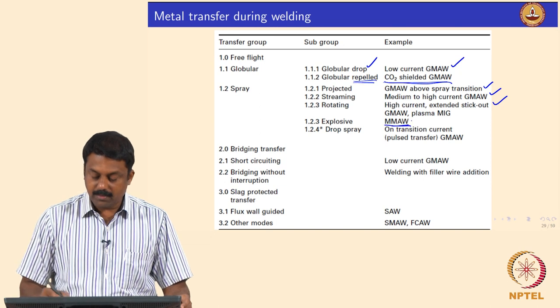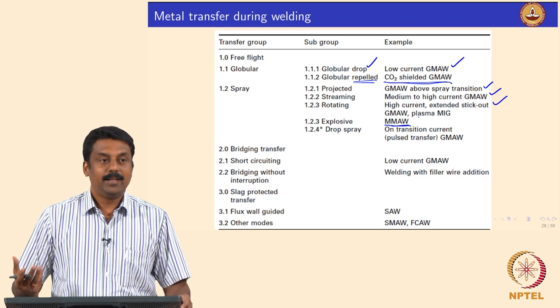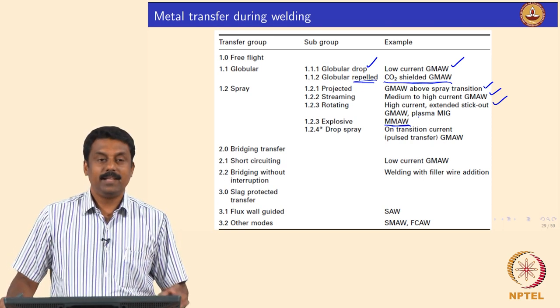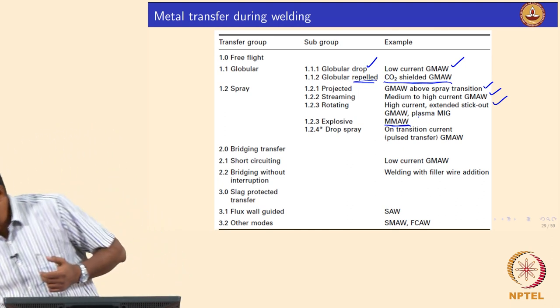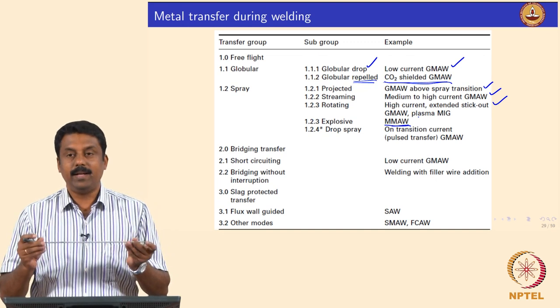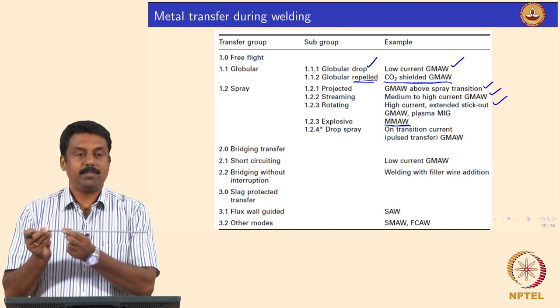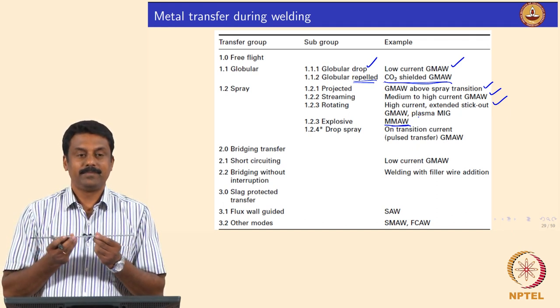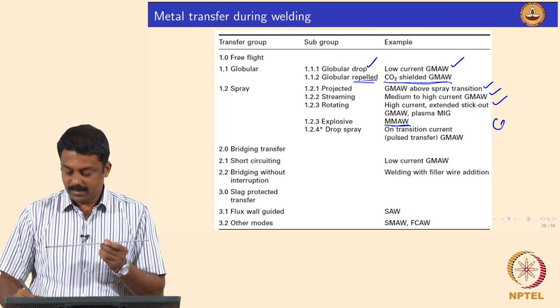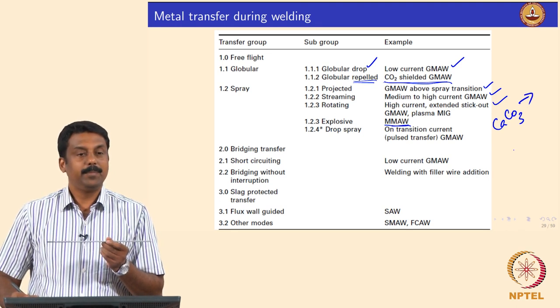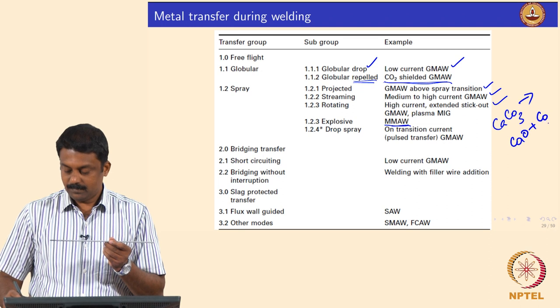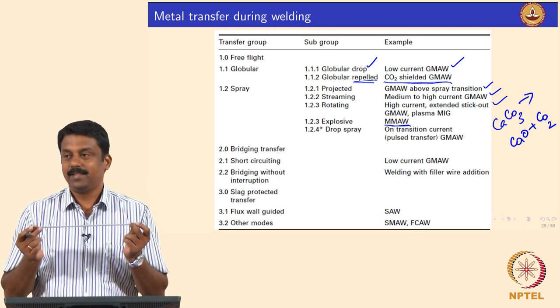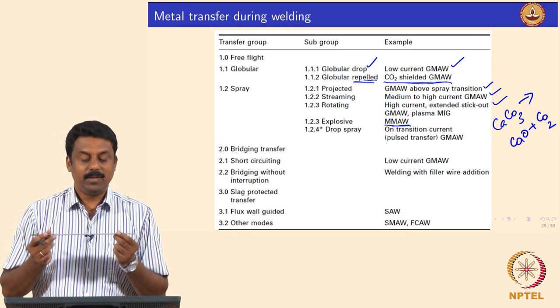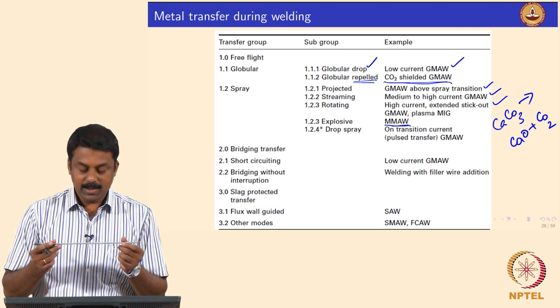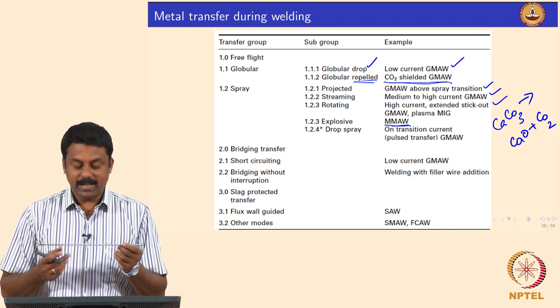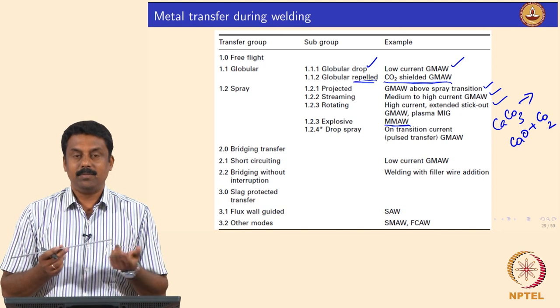Explosive transfer is very commonly observed in self-shielding. What is self-shielding? You do not give any extra shielding gas. Shielding gas is generated by the electrode itself. For example, we will go to the next slides. This is an MMAW, manual metal arc welding electrode, and you have flux on top of it. If this burns, it generates carbon dioxide. When you have calcium carbonate and it burns, it decomposes. So we generate shielding gas by burning flux. This is used for manual metal arc welding or shielded metal arc welding, and because of the CO2 generation plus the high current used to melt such a large diameter electrode, you sometimes get an explosive transfer.